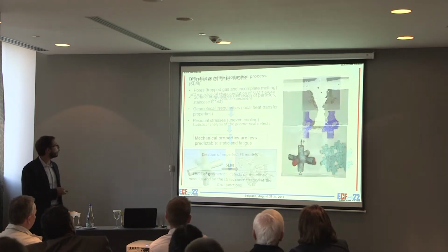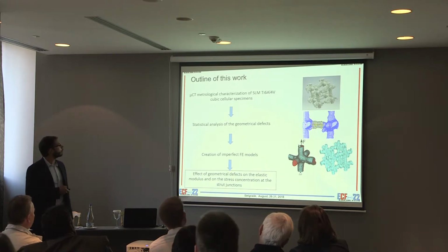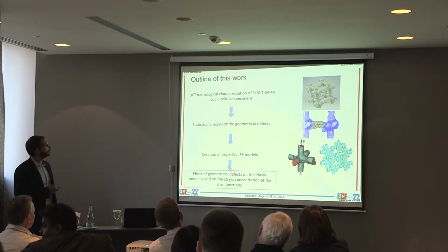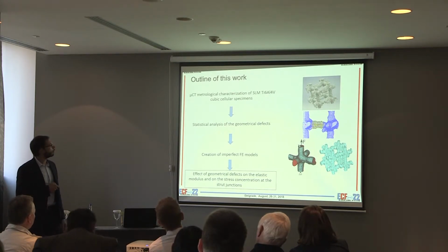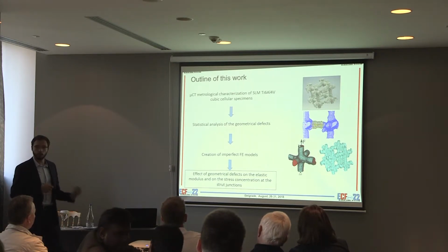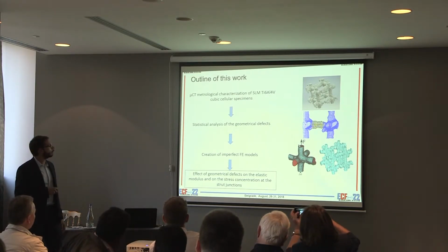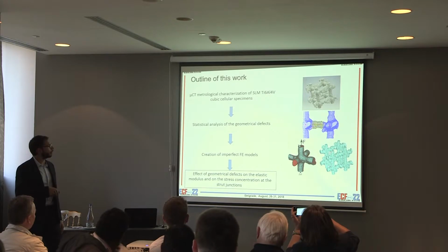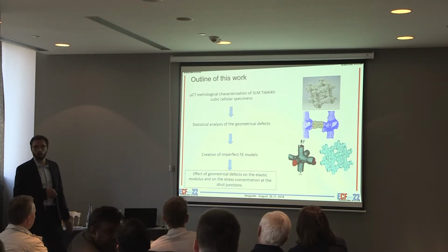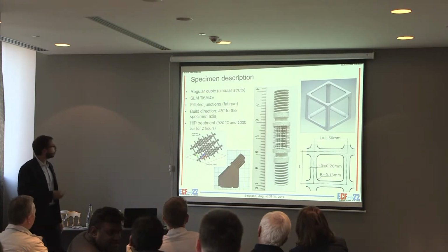the measured ones. So the aim of this work basically is to use the data from computed tomography of several samples, which is then imported in MATLAB, analyzed, and measurements are carried out, and this data is used to build finite element models which include these defects, and the results of these simulations are compared with the experimental results. So the specimen that I studied is a very simple structure.